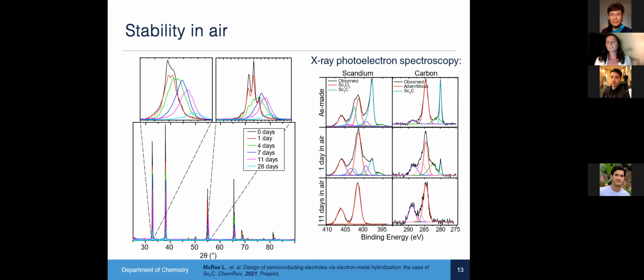Based on this data, our conclusion is that we have an amorphous oxide forming on the surface of this material first. And as we continue to let it sit in air, the oxygen continues to diffuse into the material, and eventually the bulk of the material turns into an amorphous oxide.